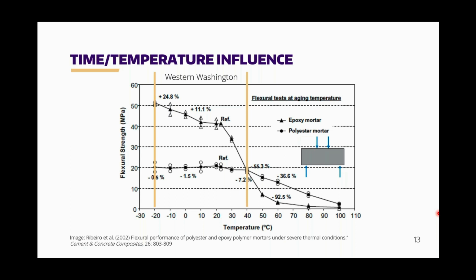So in this case, I'm showing a plot of flexural strength. This is just a 4-point bend test. And I'm showing you results for both an epoxy mortar and for polyester mortar. And because I'm in Western Washington, I gave you the range of service temperatures in Western Washington. But you can see that over that range, the difference in material properties for the epoxy mortar is quite different than the difference in material properties for the polyester. And so characterizing that is critical anytime we have a new material that comes to market.